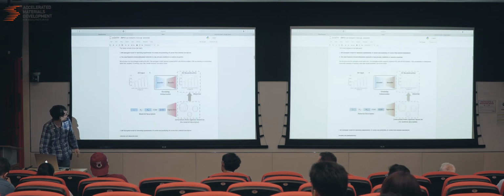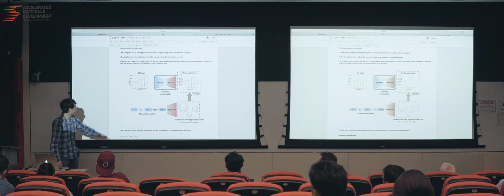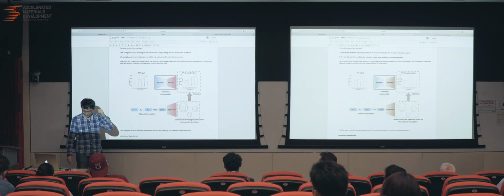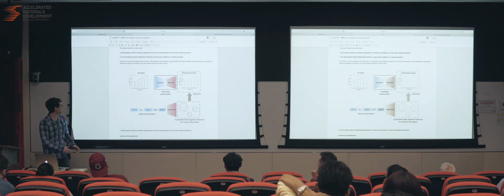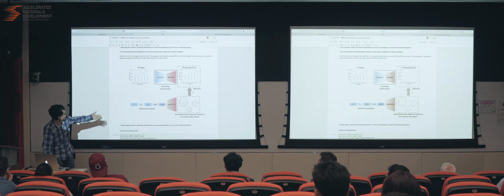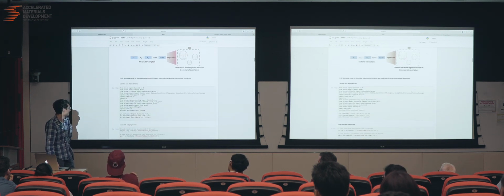All right, so the first part, as Felipe just introduced, is the surrogate model to map the material descriptors. In this case, we are looking at the bulk lifetime, the doping, and the interface recombination, to whatever you observe in the JV curves. We actually vary the light intensity just to get more information from the JV curve. It relies on two neural network models. One is a denoising autoencoder. The other is a regression model. Here we use just a standard machine learning model.